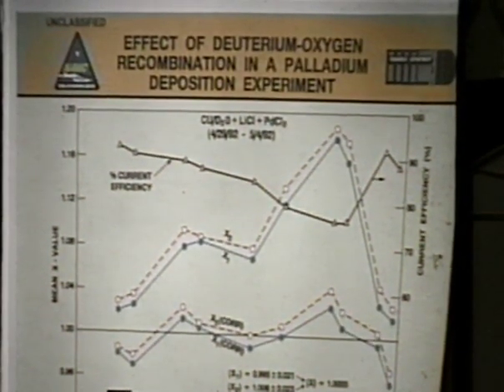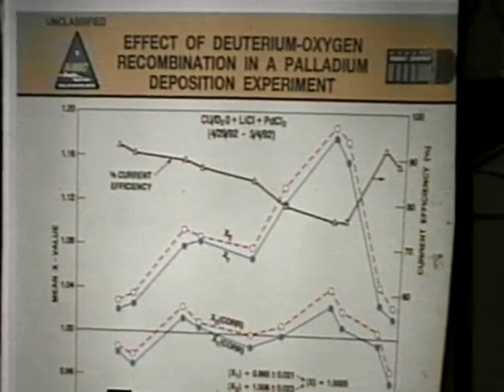It was a plating experiment. Stan Spock came up with this idea where you co-deposit palladium and deuterium at the same time. When you do this, you get finely divided palladium, and that breaks loose and gets up to the top of the cell, and on some occasions we've had explosions because of the catalytic recombination. So we know we get recombination because the catalyst gets loose, floats to the top of the cell and coats the cell walls. But this shows you that we can detect that.